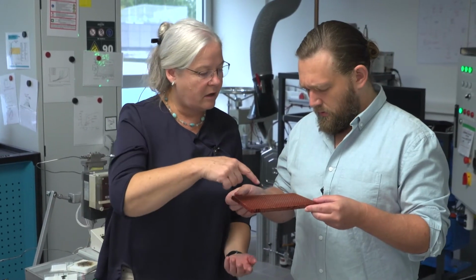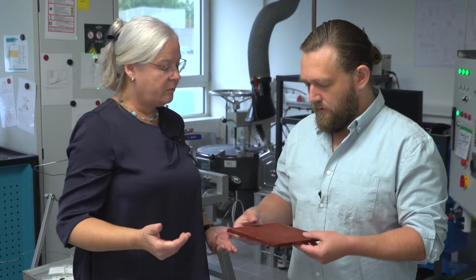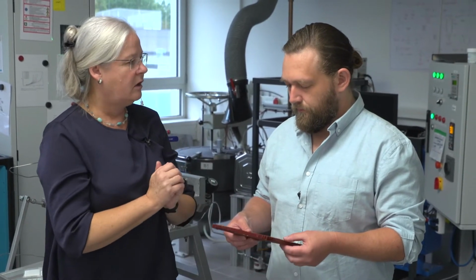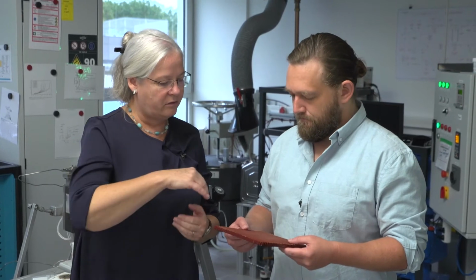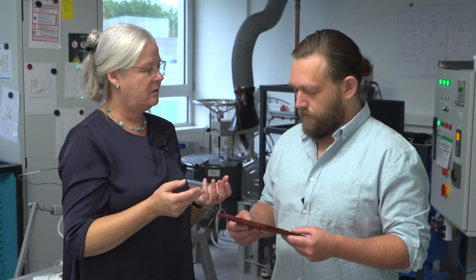No, this is aramid. Oh, this is like Nomex. Yes. So we can also use aluminum, but then the thermal conductivity is much higher from the honeycomb. And you use it for other applications. You can then embed MOFs, for instance. Metal organic frameworks. And they are normally powders, and you can handle them very easily.